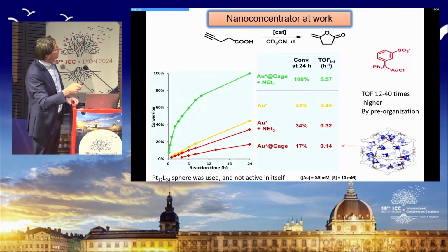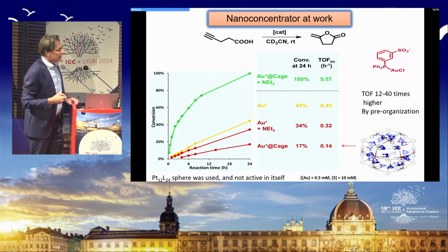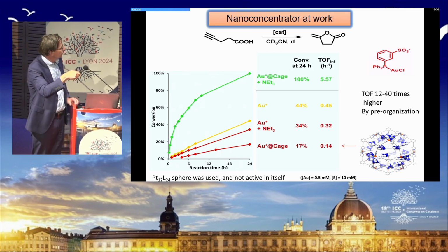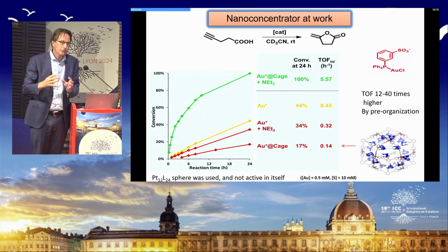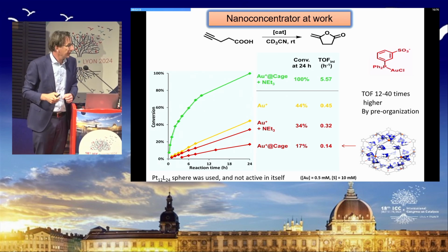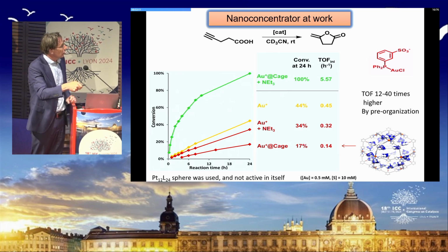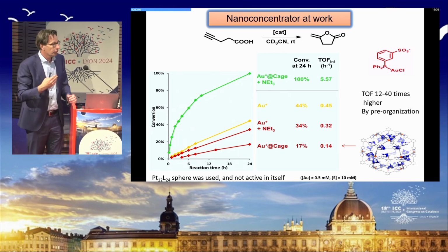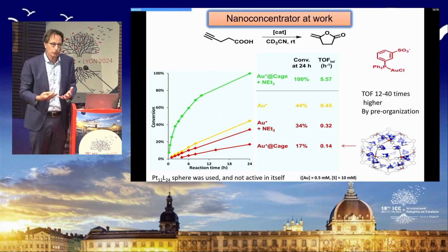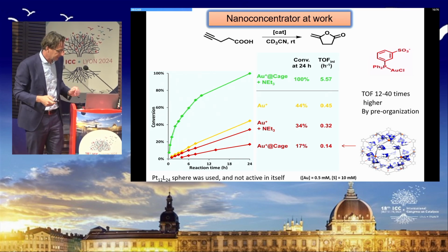And if we then do this cyclization reaction that is catalyzed by this gold complex, then you can see here all the control experiments, and here is the kinetic curve where we take advantage of the pre-organization in the cage, and we find turnover frequencies that are 12 to 40 times higher than without pre-organization. So it's just a substrate pre-organization effect over here.